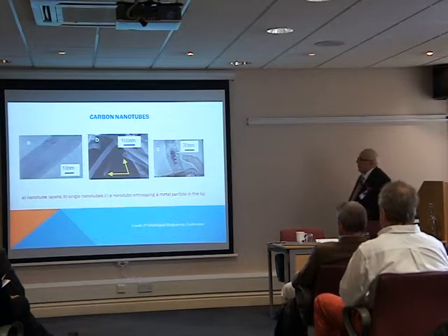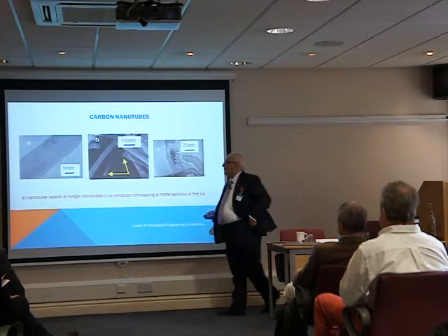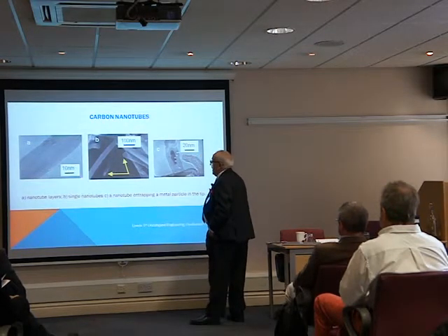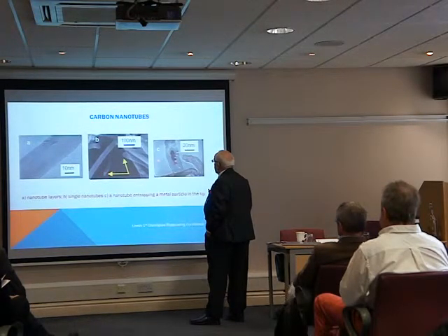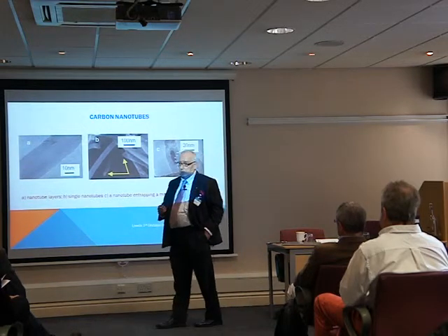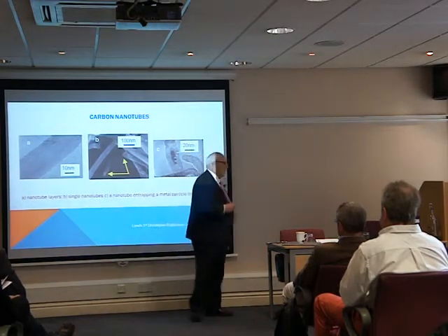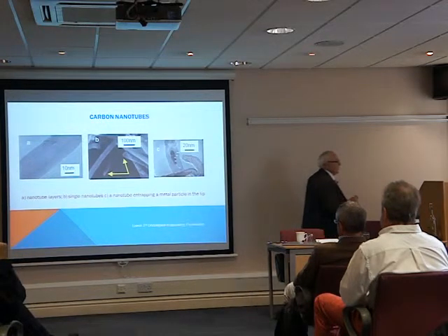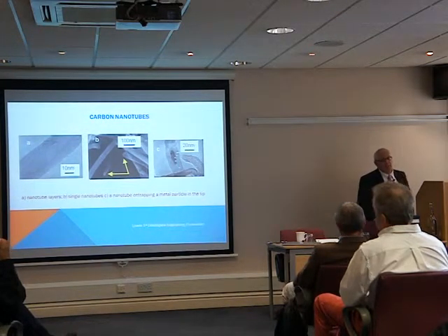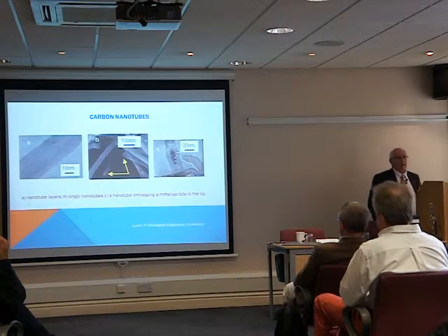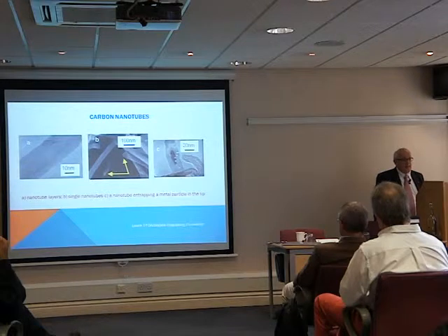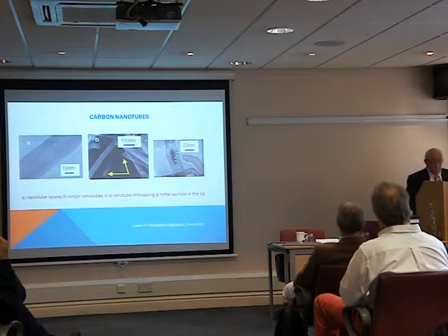These are images of a carbon nanotube built for us by a company that we work with. The scale is 10. This is a multi-wall carbon nanotube. You will see that the tip is slightly bulbous here. And this is because there is a metal impurity, largely iron. And it is this that renders, or partly is the reason, not completely, that carbon nanotubes are paramagnetic and therefore can be influenced by magnetic fields.